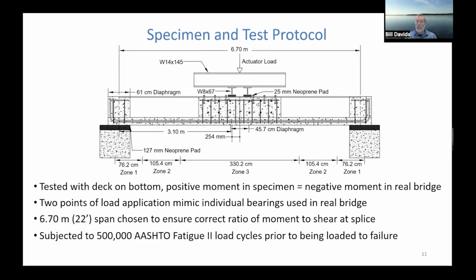It was tested upside down. So the deck was placed on the bottom so that when we push down with an actuator, we put tension in the deck and compression on the girder flange. So it mimics what happens in the real bridge when the girder's right side up. With 2 points of load application, you can see through those W8x67s that mimic the individual bearings that are used in a real bridge. Remember, we drop in girders on individual bearings and then concrete is poured.